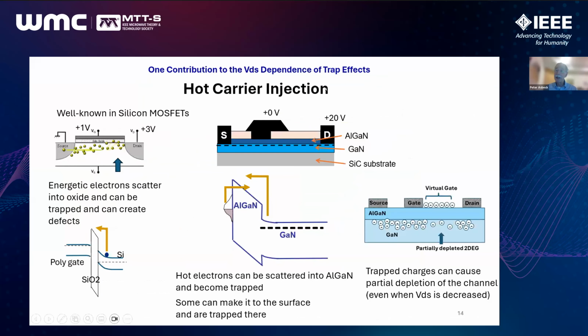One of the mechanisms that's relatively easy to understand, and the dominant mechanism, is that of hot carrier injection. This is something that's very well known in the case of silicon MOSFETs. When there's a high drain voltage, electrons traveling from source to drain can pick up enough energy that they can scatter into the overlying SiO2 and trap there and create defects.